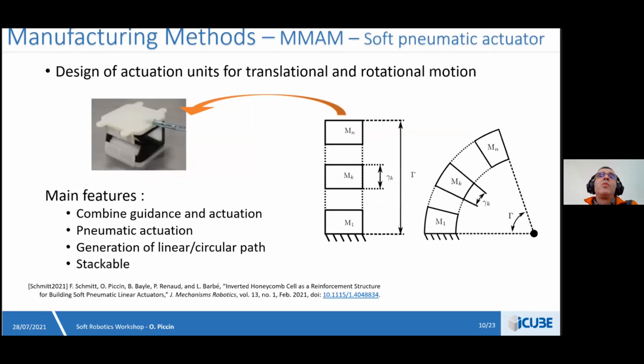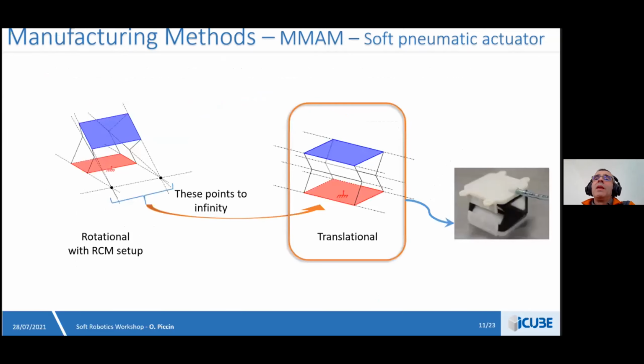So the system we fabricated using this process was a soft pneumatic actuator produced with this multi-material machine. The general design goal for this application was to build elementary building blocks or units, each of them providing a small translation displacement or an angular contribution. Each unit forms a kind of deployable mechanism, based on a kind of origami or foldable or deployable structure. The proposed architecture for the system is based on the inverted honeycomb pattern, with two configurations of the same pattern allowing for rotation or translation motion. And the objective was to fabricate this type of airtight articulated polyhedron.